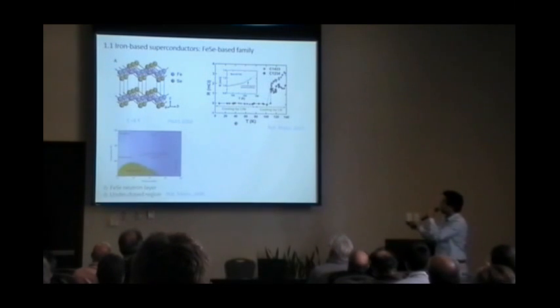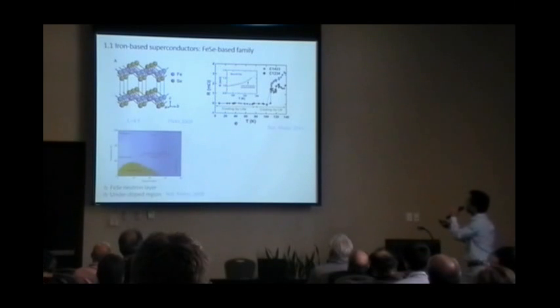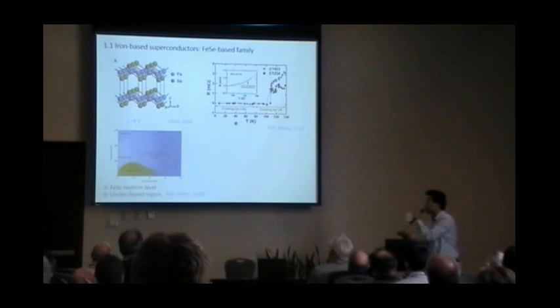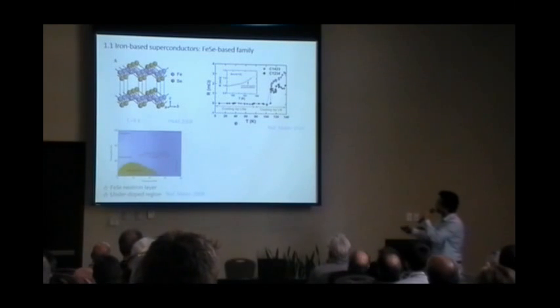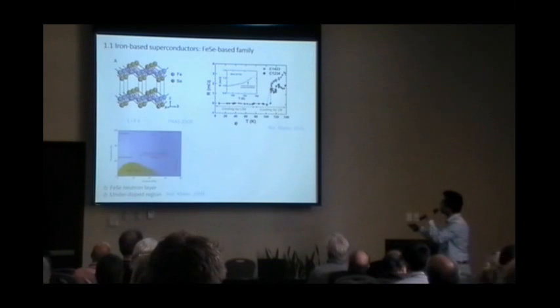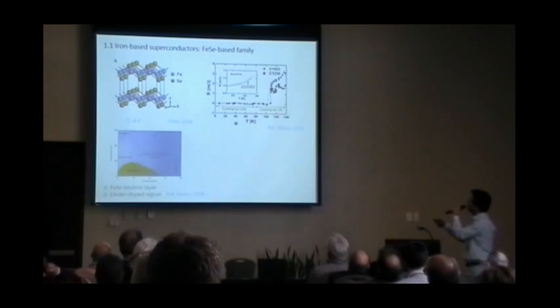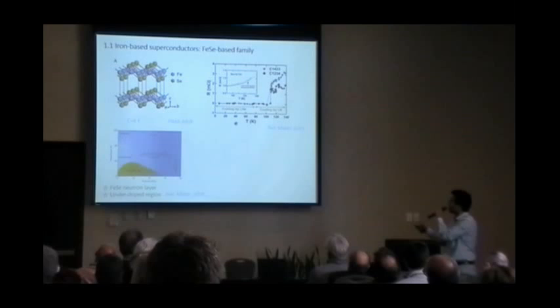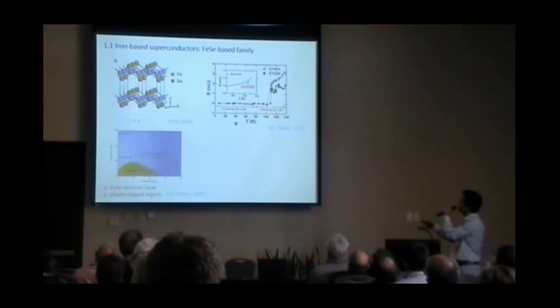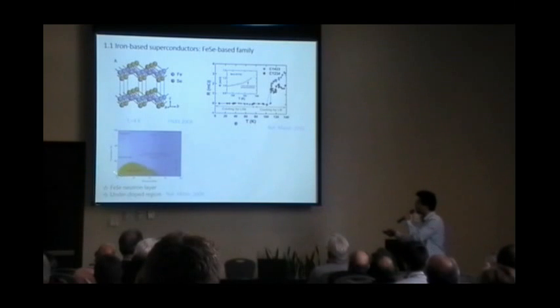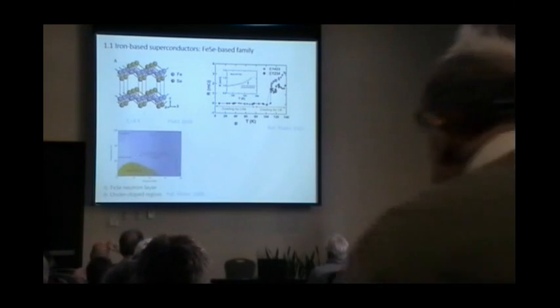Now, iron-based superconductivity is a very hot topic, the so-called iron selenide-based superconductivity. The first one is the so-called 11 system. The crystal structure is very simple, just two layers showing here. Once pressure is applied, you can see the TC is increased from 8K to almost 40K.